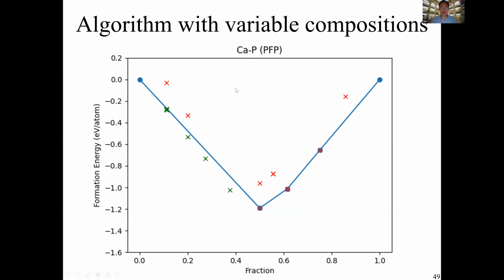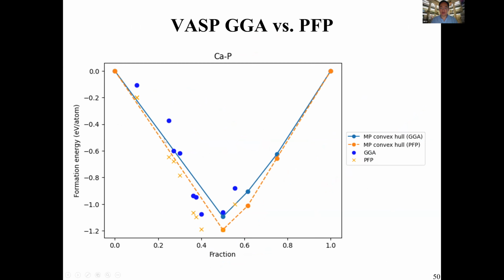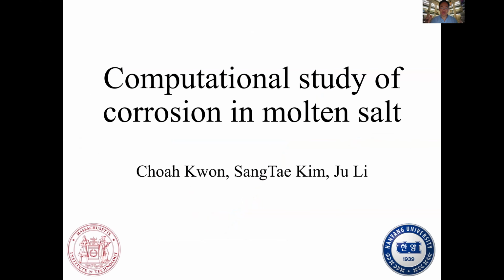So this is calcium phosphide, and by evolving with variable compositions, we were able to find, we first break the PFP hull using the initial structures that we get from the Materials Project, but then after we break them, like here, these crosses, we verified that they actually also do break the GGA energy hull. So this is ongoing. We can get about 1,000 new structures for about 3 hours of running time. And we can do pretty big structures. I think I'm going to skip over this.